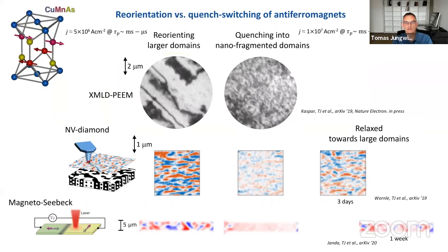So in the remaining part of the talk, let me just give you a brief flavor of a new type of switching mechanism that we discovered very recently, which is fundamentally distinct from what I've talked about so far. It's a completely different switching principle. So just to compare the conventional reorientation switching principle with the new one, which I will call from now on quench switching of antiferromagnets. In the reorientation switching, we saw these large domains, and by applying current pulses, starting from about 5 × 10⁶ amps per centimeter square at these pulse lengths, we could switch these large domains. That means reorient the Néel vector by 90 degrees.